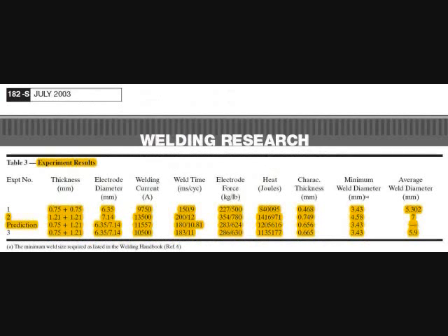In July 2003, in the Welding Research magazine, there's a paper with a table, and this guy welded 3 welds and predicted 1 weld. The first weld is 0.75 plus 0.75 with a 6.35 millimeter cap, welding at 9.75 kiloampere, 150 milliseconds, and 500 pounds. He said he used 840,095 joules to create a 5.3 millimeter nugget.